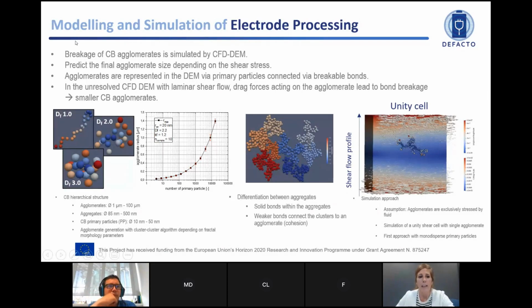So for the slurry preparation, we know that the carbon black agglomerates size distribution has a really high impact on the rheological properties of the slurry. So here, what we aim to do is to analyze the breakage of the carbon black agglomerates simulated by the CFD-DEM. Basically, we aim to predict the final agglomerate size distribution depending on the shear stress.